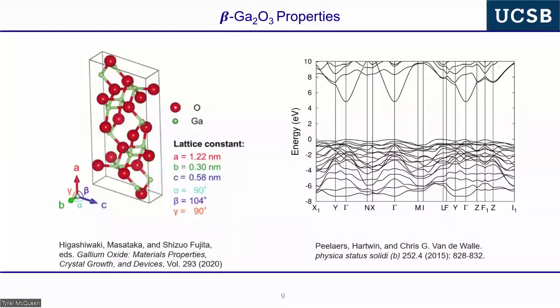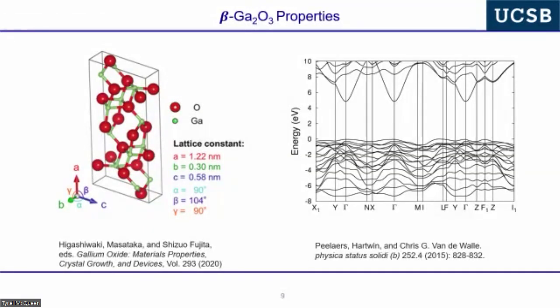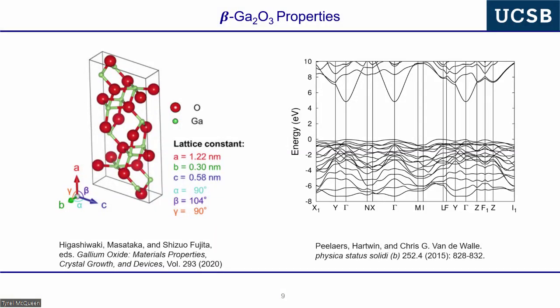And from a lot of experimental work and theoretical predictions, if we do take an electron off of the valence band, which are really coming from oxygen 2p orbitals, okay, there's a local lattice relaxation that happens on a very short time scale. I've been involved in collaborations on experiments where we actually determine the time scale of the relaxation into strong polaron states, okay? And so the holes are very heavy, and then the lattice, if we ionize and have an empty state in the valence band, immediately relaxes around that hole and forms a heavy polaron. Okay, and that happens on vibrational timescales, which are picoseconds.